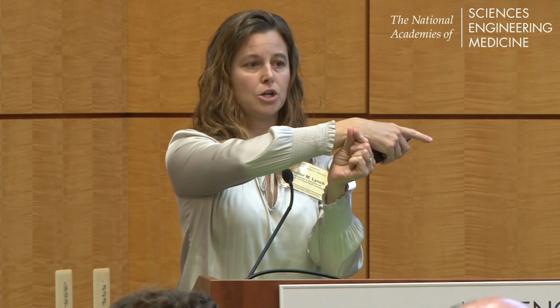The next step is to take that piece and press it into a thin film using a heat press and put it through total transmission FTIR. That way, the FTIR signal is transiting through the entire cross-section of that piece. And if these are the bands on your spectra off the ATR, then all of a sudden you start to see these bands when you're doing the total transmission. You know you have more than one polymer inside that piece of plastic.